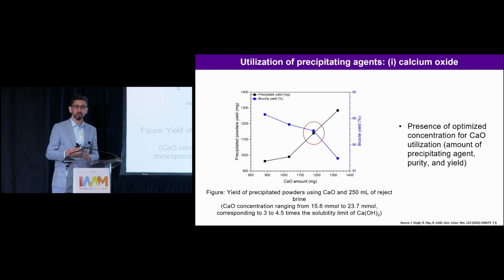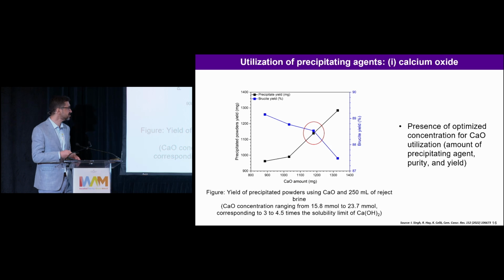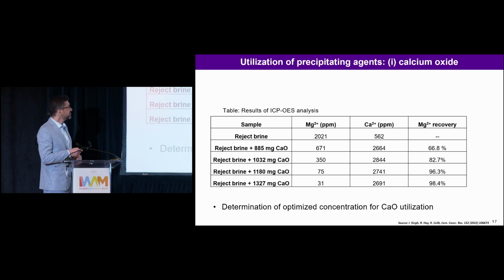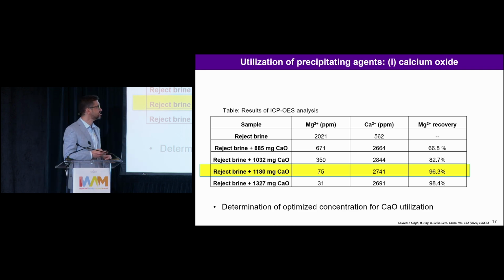And of course, to precipitate magnesium hydroxide, it requires some optimization process. We vary the calcium oxide amount and find this sweet spot with respect to precipitated powders versus brucite yield and optimize our process. After this optimization, we did ICP-OES to measure the cations in the system, and the recovery is around 96%. 96% of the magnesium is recovered after this process.